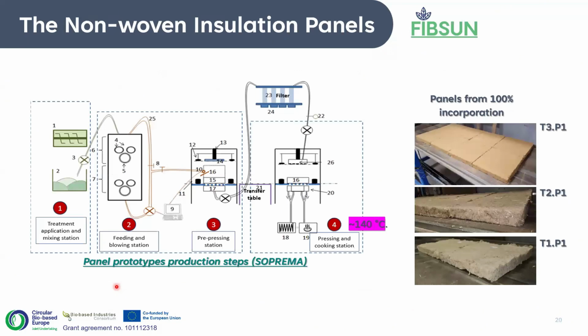So here we have the schematic of the process they've employed in making this product. Of course, first comes the mixing stage where the fines and the binders are mixed together. Then this material is blown into another stage. From this stage, the mixing is further consolidated, and then the material moves into a cooker. So before pressing, the material is allowed to cook for a certain period of time before it is pressed at around 140 degrees Celsius. So I just give a brief idea of the nature of the panel with 100% wood or 100% short fibers, and this is the 100% super short fibers.